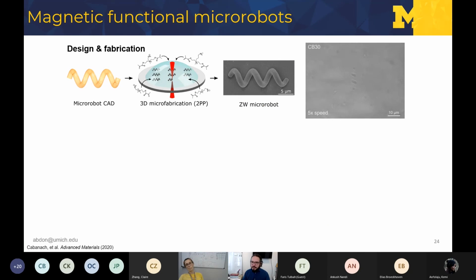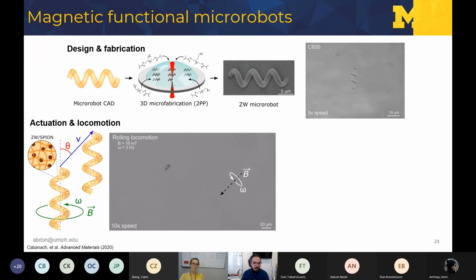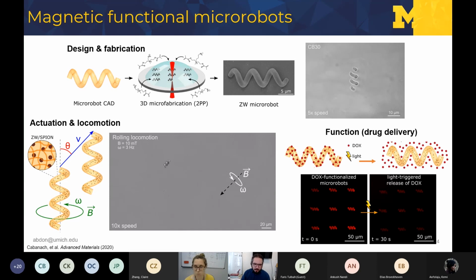So you can see here, we designed these helical robots, and I'll talk about this helical shape in a second. But we use these zwitterionic materials to 3D print these fully zwitterionic micro robots. And the reason for this helical shape is that we're using this shape for magnetic actuation. So during the printing process, we embed SPION particles, superparamagnetic iron oxide nanoparticles, and we use rotating external magnetic fields to rotate these helices. So we're literally drilling through the fluid at low Reynolds numbers, right? So you can see that by controlling the field and the frequency, we can get different types of locomotion, and then we can encapsulate some drugs for targeted and on-demand stimulus responsive delivery of therapeutics.